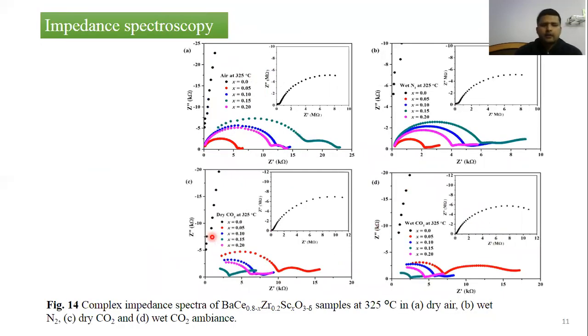This is the impedance spectroscopic data and shows the Nyquist plot of the samples at 325 degrees Celsius measured in air, wet nitrogen, dry carbon dioxide, and wet carbon dioxide. Here we can observe that the wet atmosphere shows high conductivity as compared to the dry. The reason may be the incorporation of water molecules, which leads to proton migration, increasing the conductivity in wet conditions.